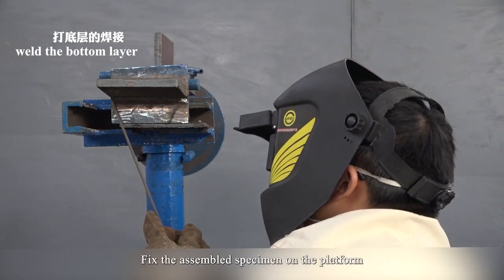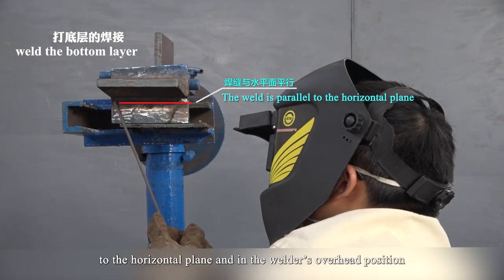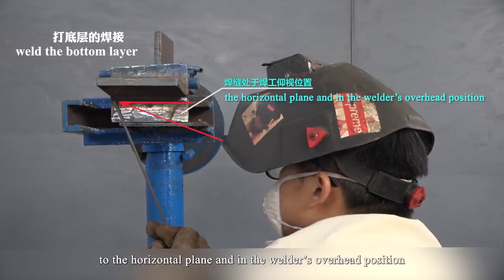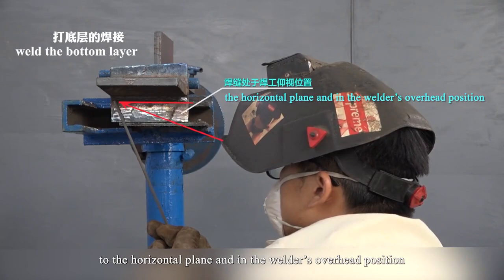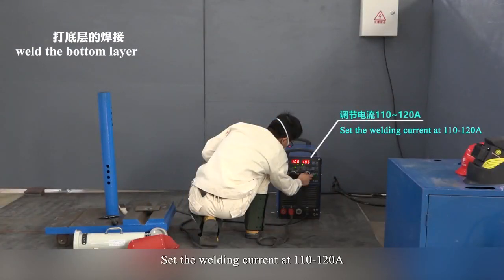Fix the assembled specimen on the platform with the weld parallel to the horizontal plane and in the welder's overhead position. Set the welding current at 110 to 120 amperes.